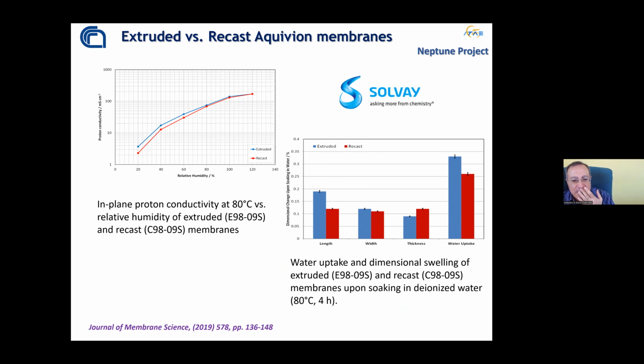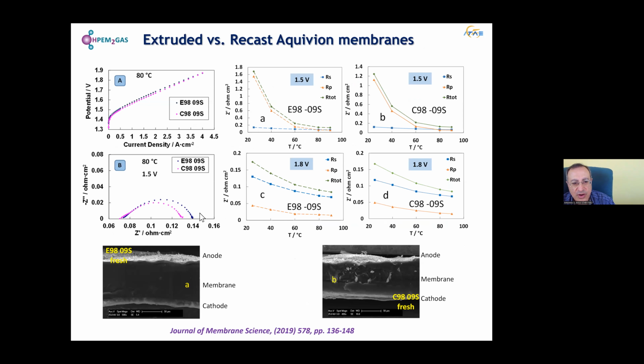Now, coming back to the membrane, we have discussed a little bit about catalysts, but now let's come back on membrane. So how to assess the properties of the membrane? We measure proton conductivity as a function of relative humidity, and we also measure the so-called dimensional swelling, because we need to have a stable membrane. This is for the Aquivion.